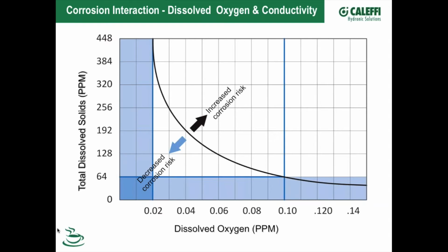And what this is really saying is that you can control corrosion largely for most metals by either A, limiting the amount of dissolved oxygen in your system, or B, reducing your total dissolved content. So as an example, if you look along the y-axis at total dissolved content, you see a blue line at 64 parts per million. And if you look at the curved graph, on the far right side, if you have non-conductive water, say total dissolved solids of 40 parts per million, then it doesn't make any difference how much oxygen you have dissolved in your system, because there is very little conductivity in the water. And we like to explain corrosion, in analogy terms, like your car battery.